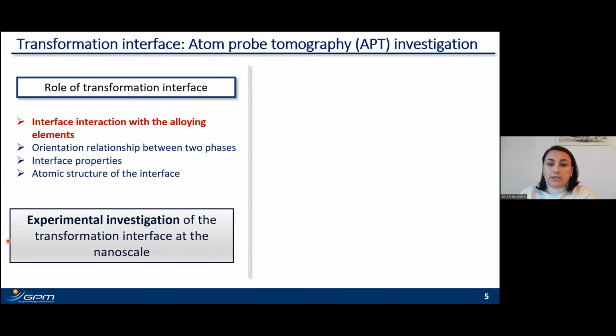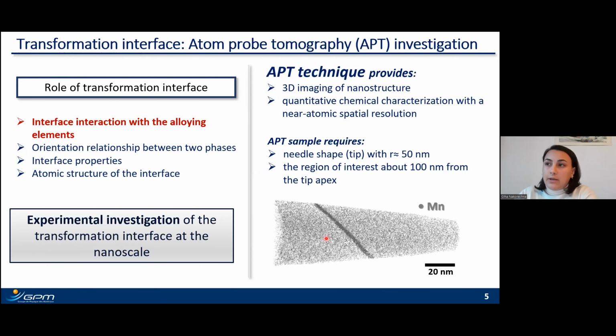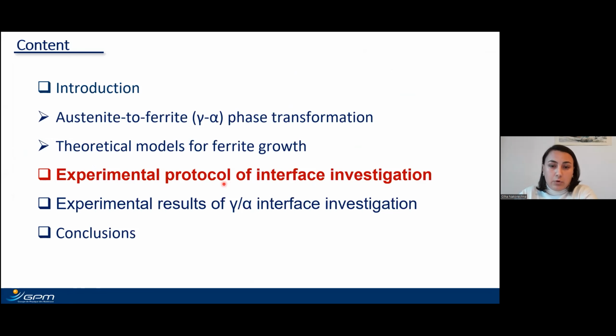In any case, we can summarize that the most interesting things during the transformation processing are happening at the transformation interface. And there are many open questions regarding the role of the transformation interface during the phase transformation. But this presentation will mainly concentrate on the interface interaction with the alloying elements, because it is one of the main factors that retards the interface propagation and thus affects the transformation kinetics. One of the main tasks of this study was to get experimental data of nanoscale solute redistribution at the transformation interface. And atom probe tomography used in this work is one of the most promising techniques to reach this aim. But in the case of APT investigation of a transformation interface, it is necessary to use a site-specific sample preparation procedure. So it will be explained in the following part of my talk.